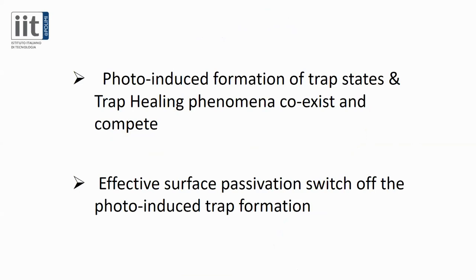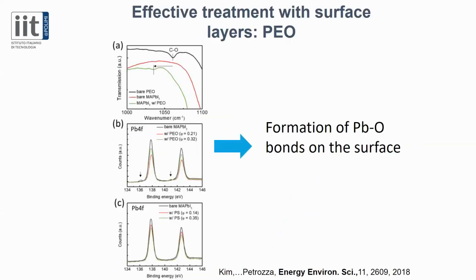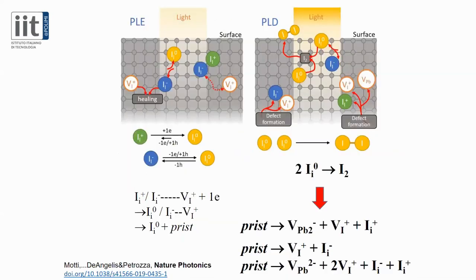So photoinduced formation of trap states and trap healing phenomena coexist and compete, and effective surface passivation can switch off the trap formation. What is happening? And here I'm close to finishing my presentation. What is actually happening? The polyethylene oxide is forming lead oxide bonds on the surface, so it's passivating the undercoordinated lead on the surface. Nothing directly to do with the native defects in the bulk. Nevertheless, this is the landscape, so this is the explanation we have.